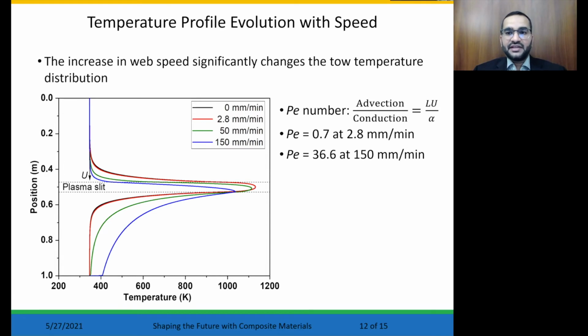The temperature profile in the three regions evolved with increased web speed because of the heat advection by the moving tow. The temperature decreases in the pre-plasma region and plasma region, but it increases in the post-plasma region. Most importantly, the uniformity of temperature in the plasma region was reduced with increased web speed. The changes in temperature profile result from the increased Péclet number with increased web speed.